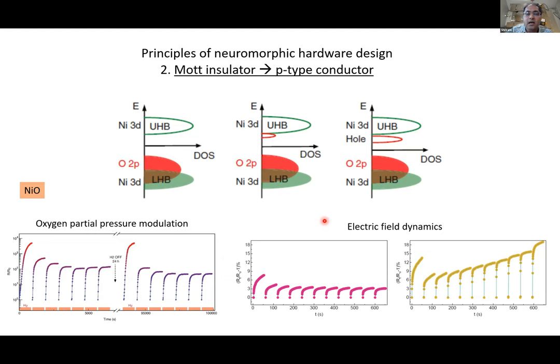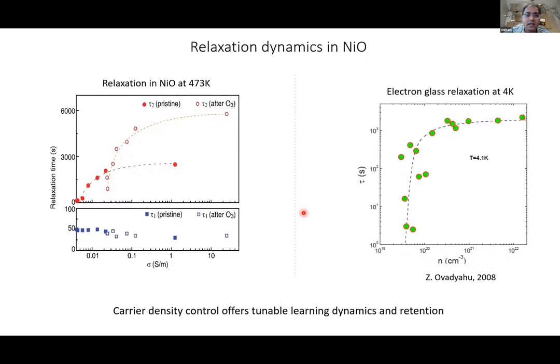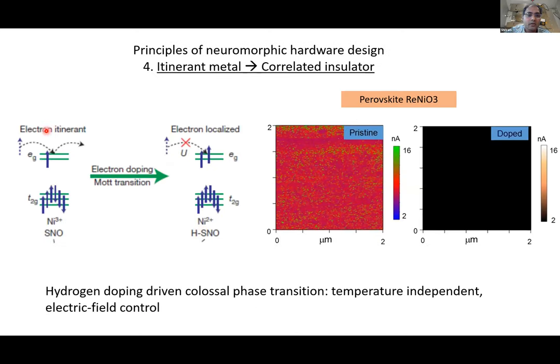But basically, there are some subtle differences like that in terms of the dynamics with nickel oxide versus nickelate. The physics of what we are doing here with the nickelates is that we are basically going electronically between a nickelate and a nickel oxide. It's a perovskite structure-wise, but electronically it's behaving as a nickel oxide Mott insulator. That's how we are able to go from a metal to insulator phase transition in this particular compound.